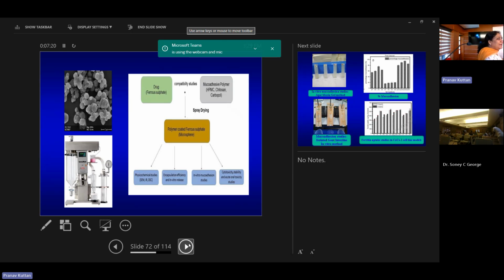And this test is generally conducted using DSC. DSC of the material will be checked. Then IR will be checked like that. Then once that compatibility test is passed, we will go for the spray drying, and we will get different sized particles. This is an example of a micron-sized particles SEM image. And we conducted different characterization as usual, like SEM, IR, etc. Then we will find out the encapsulation efficiency that has to be optimized. That encapsulation efficiency has to be sufficiently high.